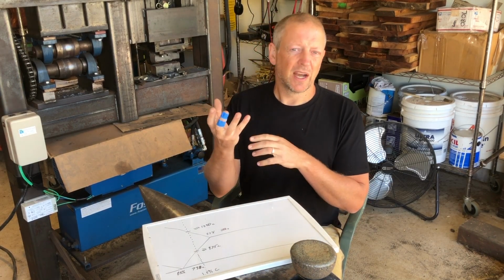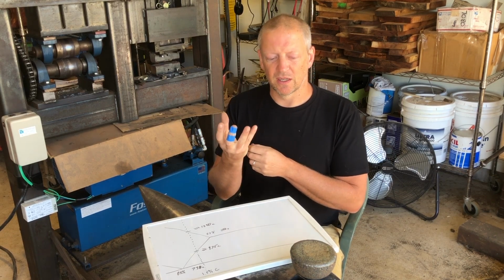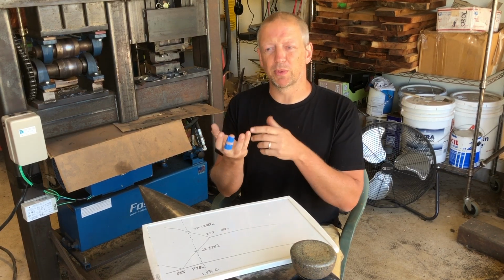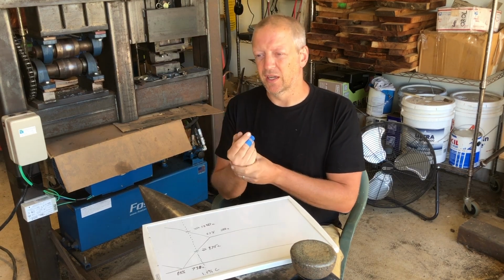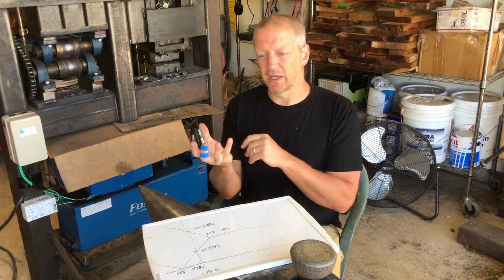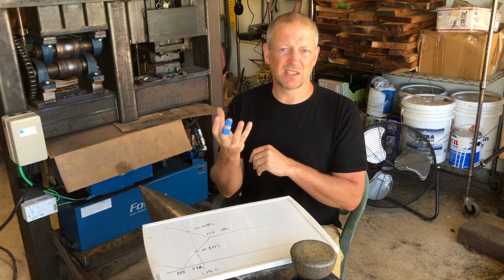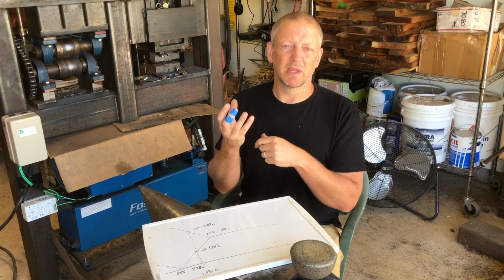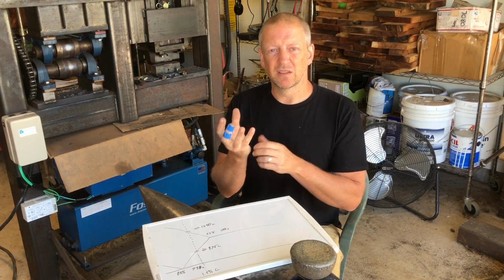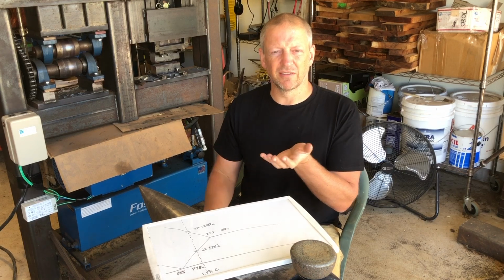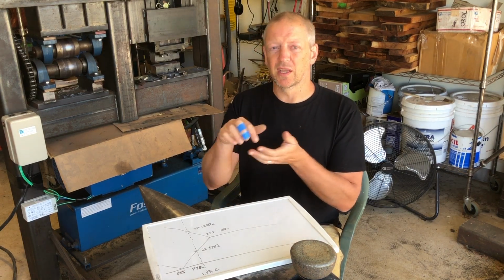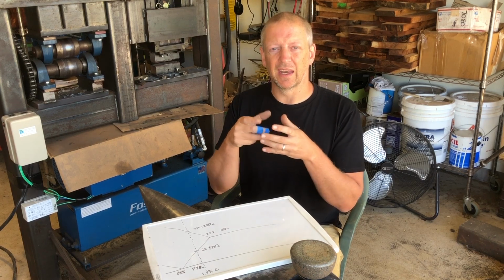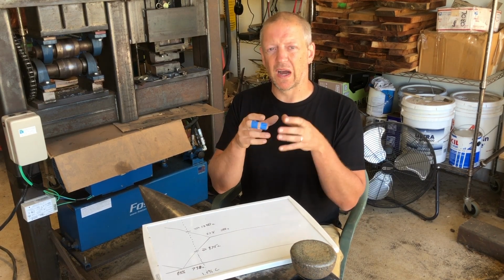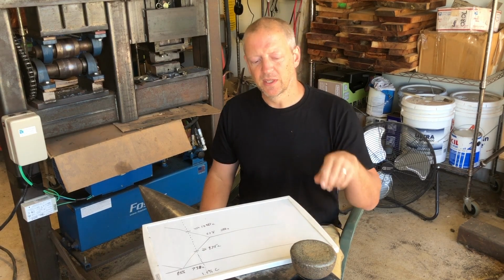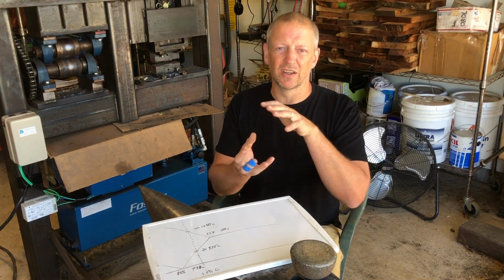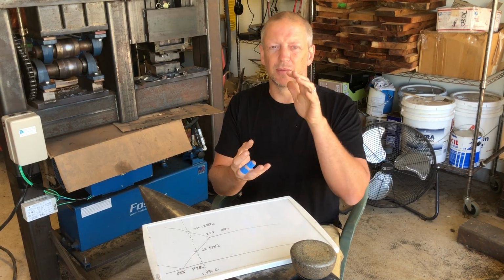However, hot shortness was an issue, and part of their goal was to replicate how historical smiths might have created this case of extremely low carbon steel or iron, sort of as an envelope on the outside of the ingot. Now, in the process of oxidizing the outer portion of the ingot, you do also oxidize out the sulfur. So they were creating a case or a jacket on their ingot that was very low carbon, very low sulfur.